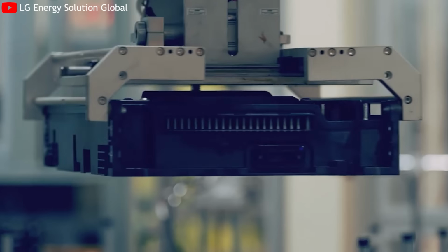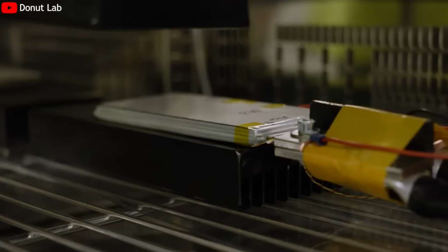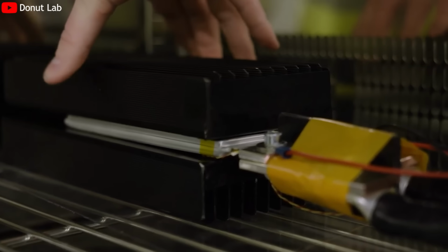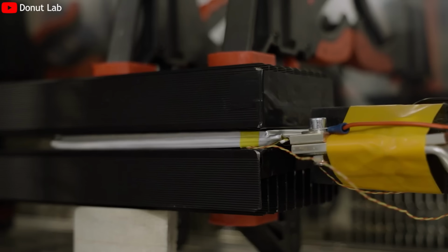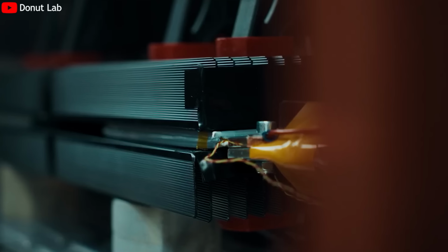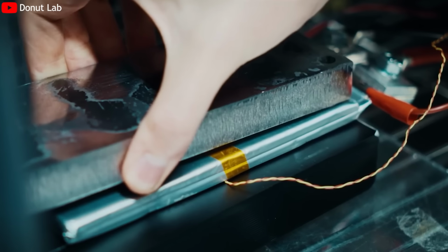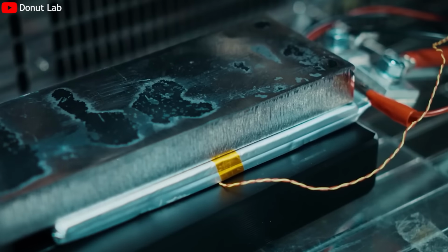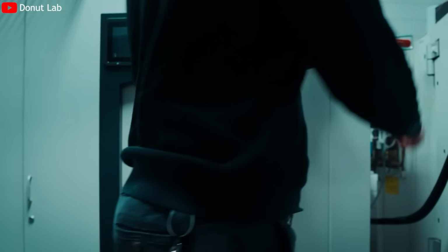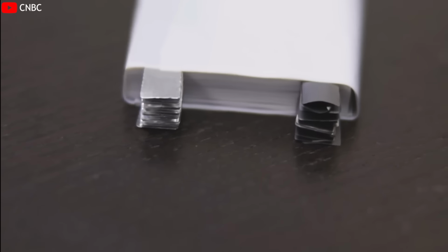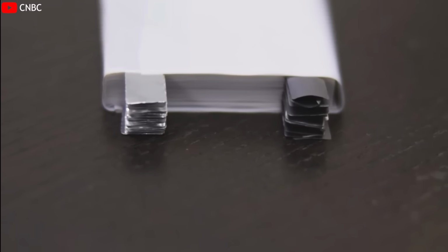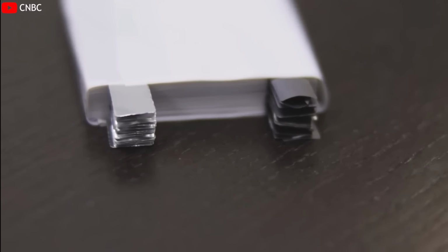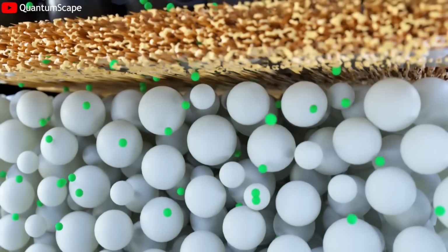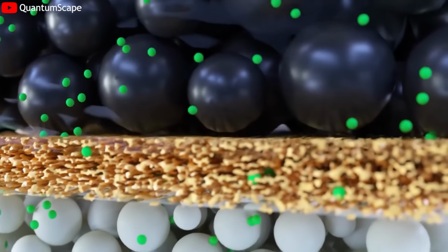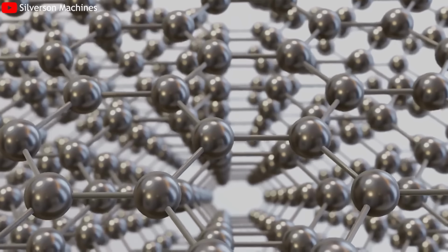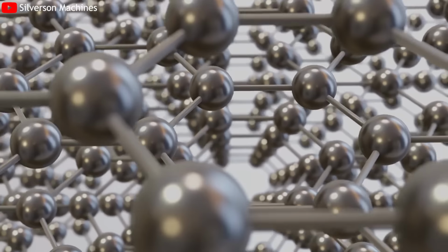The safety risks are substantial, yet in this case, despite the seal compromise and visible swelling, the Donut Lab cell continued functioning and was able to accept charge afterward. That strongly suggests that whatever electrolyte system is inside does not behave like a conventional flammable carbonate liquid. This is the first major conclusion. The swollen seal does not prove the battery is revolutionary, but it significantly weakens the idea that it is a standard liquid lithium-ion architecture. If it is not a typical liquid electrolyte system, what could it be?